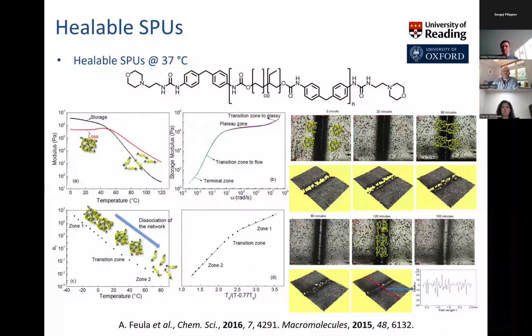So working with materials very similar to what I've shown you before, ethylene cobutylene systems with urethane end groups, we were able, in collaboration with Clive Sivier's group at Oxford, to study the mechanical properties of these materials. And shown on the right-hand side are the images of how these materials heal at body temperature, around 37 degrees C. And the profilometry plot at the bottom right-hand corner of this slide shows you that after healing for a little over 2 hours, the damaged zone has been repaired.